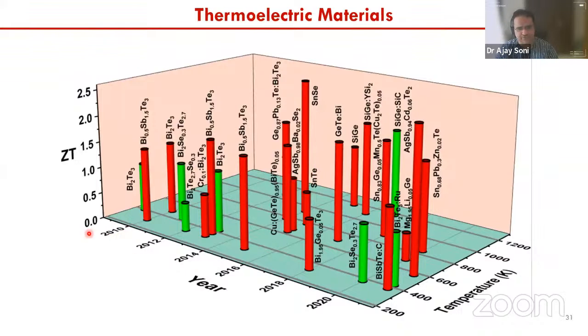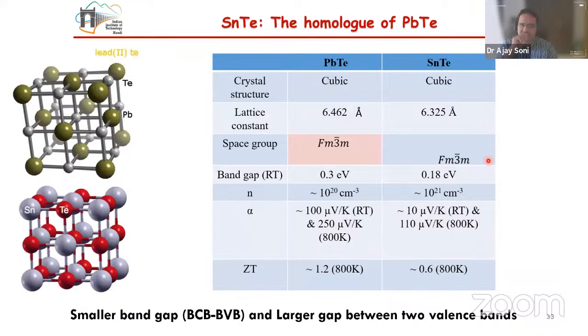And if you look at the evolution of the research from the last 20 years or so, you can see there are a lot of materials. The red color represents the p-type material, and the green color represents the n-type material. So it is the combination of n-type and p-type materials, and this is the temperature range. You can see people have reported figures of merit of nearly 2.4 or 2.5. Okay, so in our group we work on... I'll take another 5 minutes to complete my talk. I will just discuss the material aspect of the research we are doing in the lab. So SnTe is a material which is the homologue of PbTe, which is the champion material, which is already in commercial application. But the problem is that it has lead.